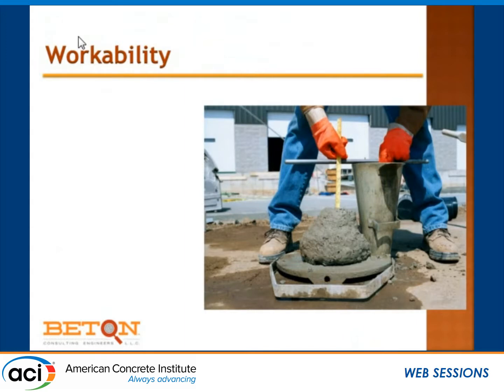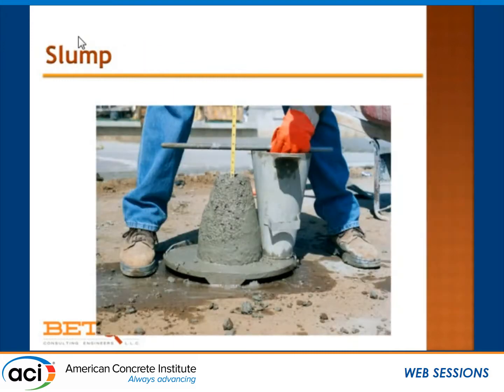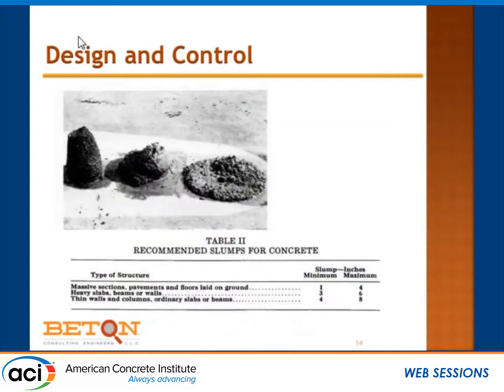And this is another number that we often associate with Abrams, and that we often associate measuring the quality of concrete, because at the time that Abrams did his work, these were measures of the quality of concrete, because the only way to go from this horrible and dangerous material to this incredibly safe material was to remove water. And, you know, if you look at the specification, I specified a maximum 3-inch slump, and it came from a table, this one in particular, that says for massive sections that I want a slump, floors laid on ground, for example, I want a slump from 1 to 4 inches, so 3 is a nice reasonable number.